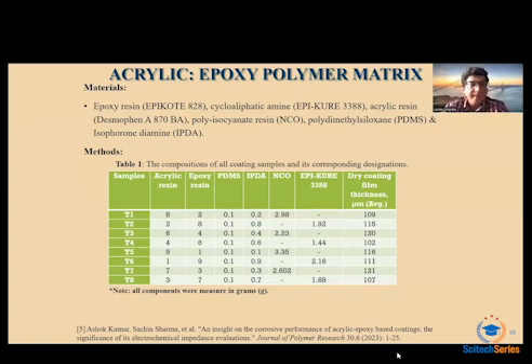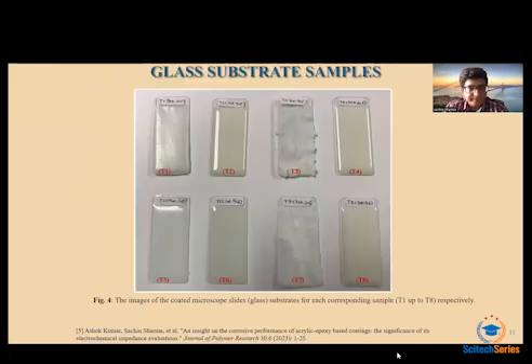All right. And then finally, when the curing agent was added, a clean glass rod was used, and it was manually stirred for 2 to 3 minutes before it was applied on both sides of the mild steel substrate. Okay, the remaining coating was also applied on one side of the glass substrate, and the remaining coating was placed in a petri dish, so that we could get the film to conduct other testings. So this is the glass substrate samples that was prepared for all the samples ranging from T1 to T8.